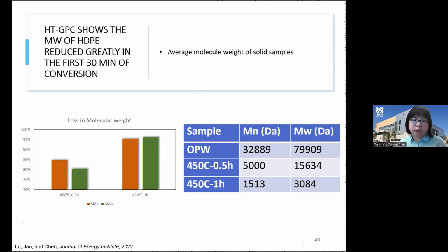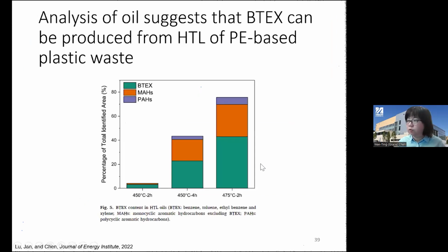However, I want to show you that we also monitor the molecular weight of this polymer at different reaction times. And you can see that within 30 minutes, this technology has significantly reduced the molecular weight from around 33,000 dalton to 5,000. But this 5,000 dalton polymer is actually still solid. It's not totally broken down yet. So it takes another 30 minutes to further break it down into something waxy. And if we wait longer, it becomes oil.